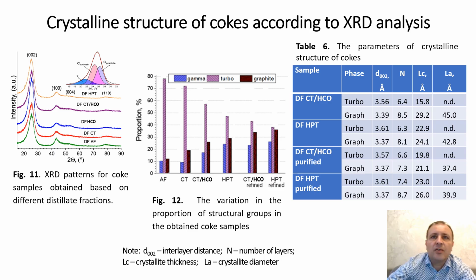XRD patterns of the coke are shown in figure 11. All the samples are characterized by wide diffraction reflections typical of carbon material containing disordered structures. The most intense asymmetric peak with a maximum at 2 theta around 26 degrees corresponds to the reflection from the 002 plane of graphite-like structures. Weak wide reflections from the 100, 004, and 110 planes are also observed in other regions.